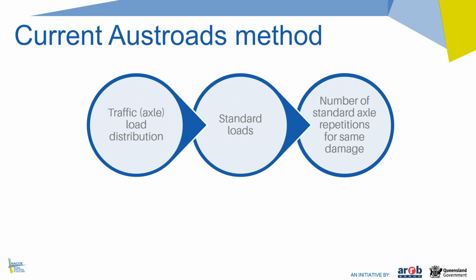In the current Austroads method, all loads in the traffic load distribution are converted to a number of standard axle repetitions that are assumed to cause the same pavement damage as the actual traffic, and that conversion is done using what are called standard loads. The standard loads are based on peak surface deflection for different axle group types being the same as under a standard axle. So that means that axle groups causing the same surface deflection are assumed to cause the same pavement damage.